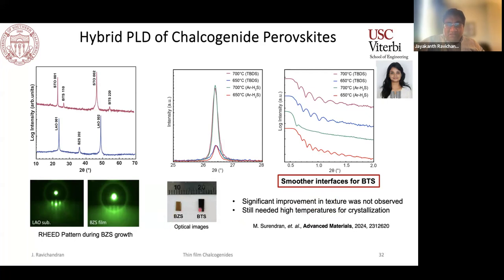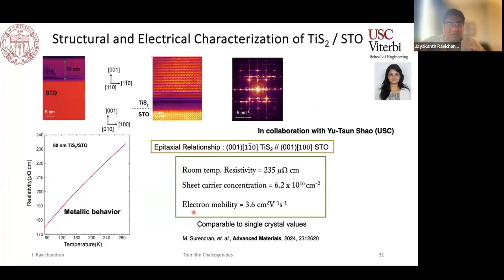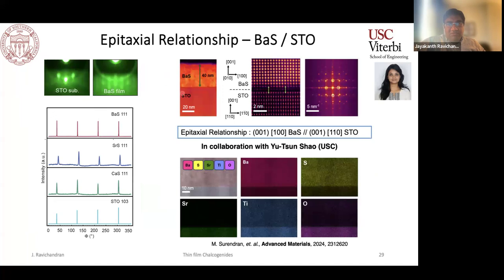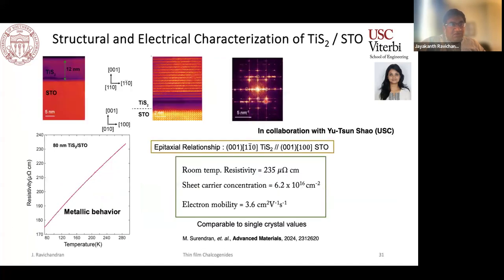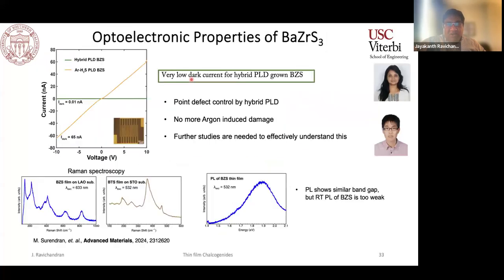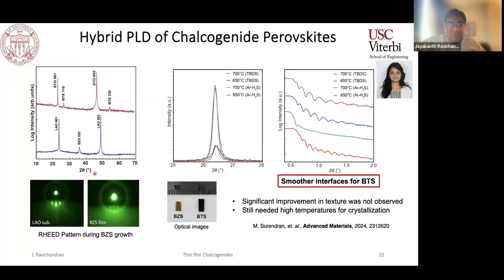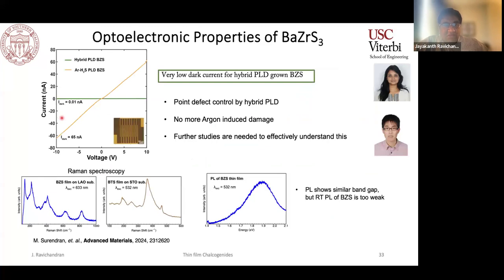about these ternary systems, because as I showed earlier, we can grow barium sulfide thin films of fairly good epitaxial quality. We can also grow titanium sulfide thin films of fairly good epitaxial quality. But when you combine both of these, the growth of the ternary system seems to be much more challenging. So this vapor pressure mismatch still seems like an issue that we'll have to work on. We have some new ideas that we are coming up with to try to solve this issue.